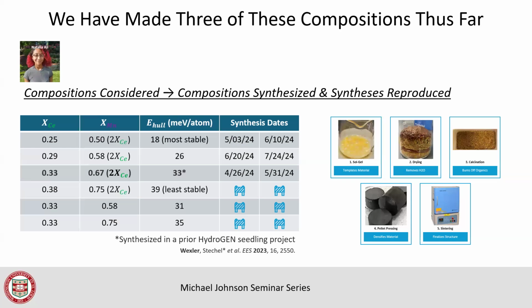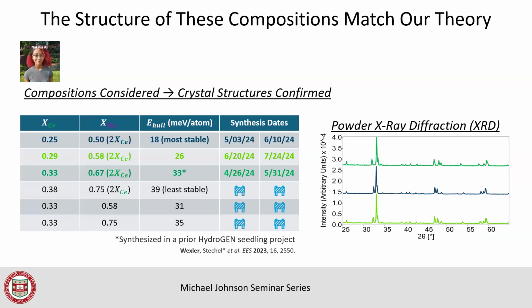Then we press pellets. So you can see the transformation. You go from something that almost looks like an uncooked egg to a pellet. It's black. We then do a process called sintering. Sintering further refines the structure. We end up with a material that's really well ordered, has the right composition, and is ready to be characterized.